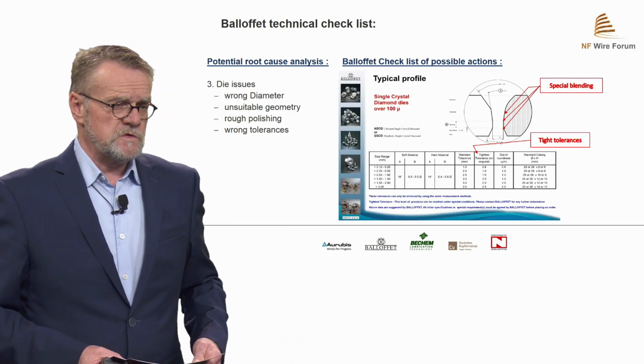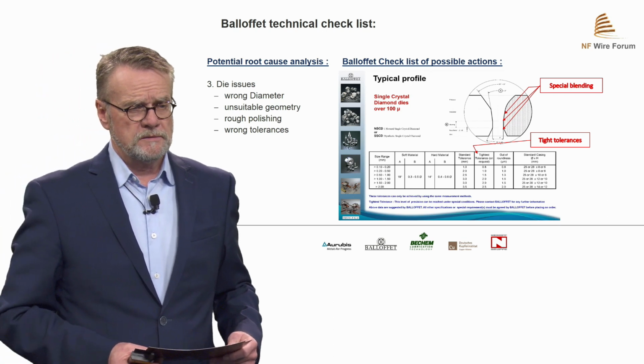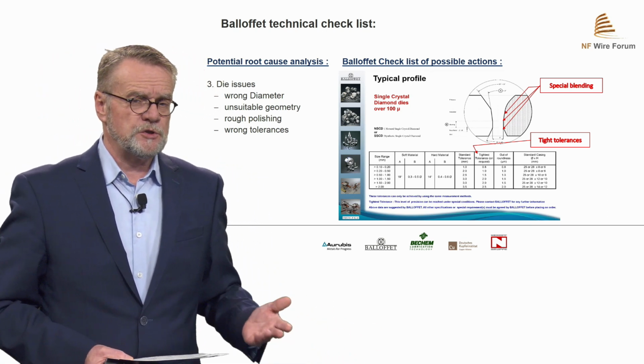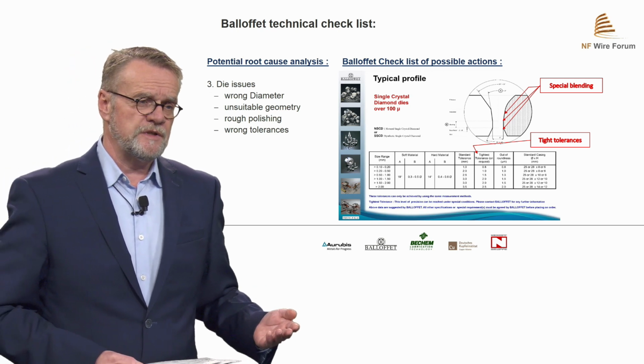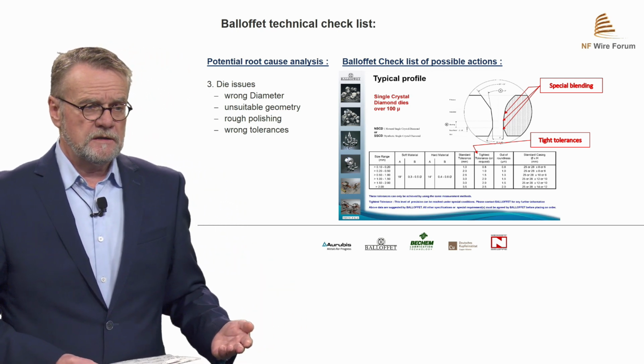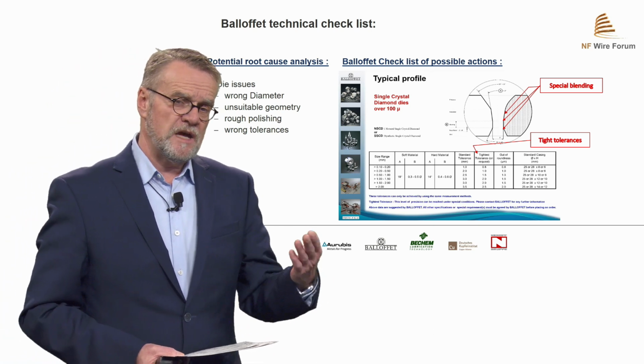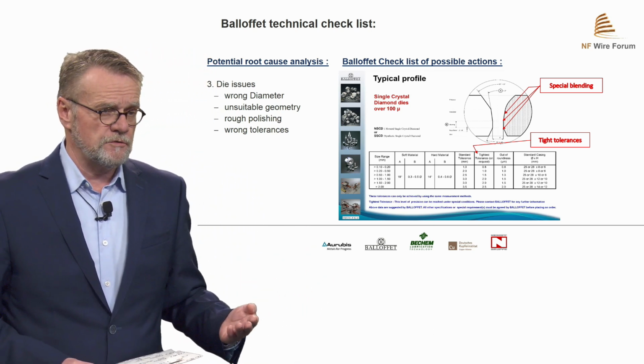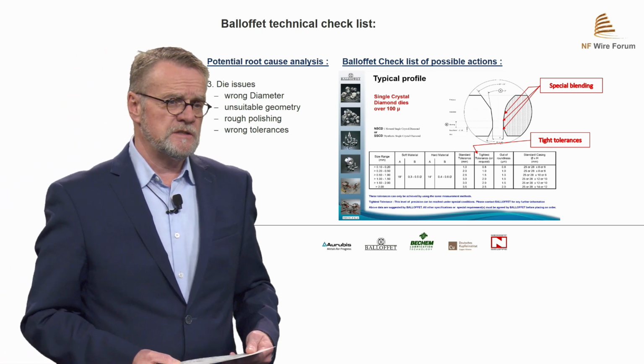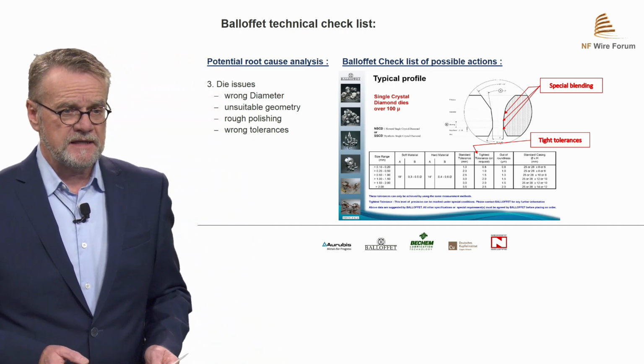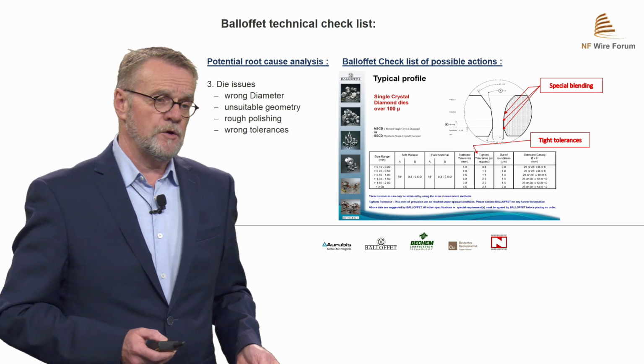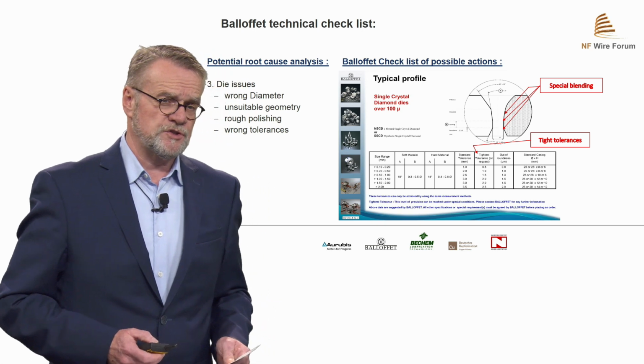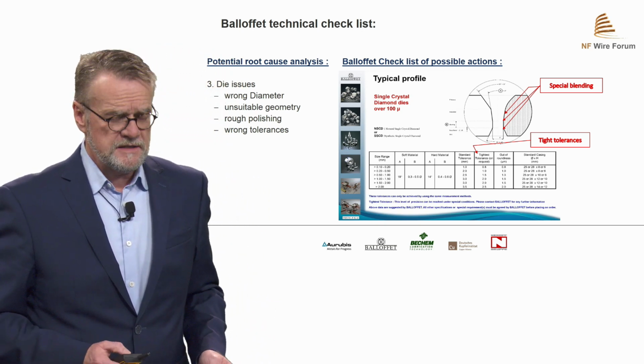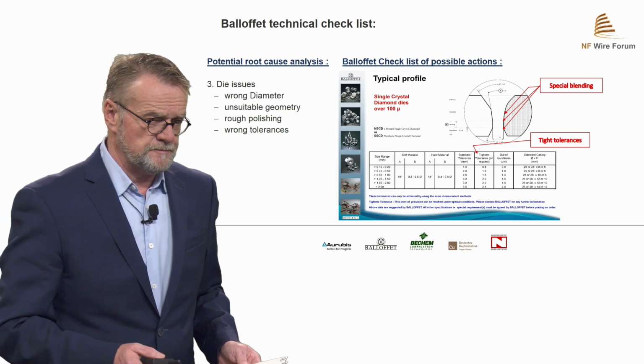On the dies, we also have many issues to control. The diameter at first, but also the non-fitting geometry. We have to check the polishing, and we also have to check if we have used probably the wrong tolerances. For this, we have a special specification where we see in the die if the blending is well made, and if on a multi-line machine we use tight tolerances, because from time to time we have 500 dies on the machine, and these have to fit.